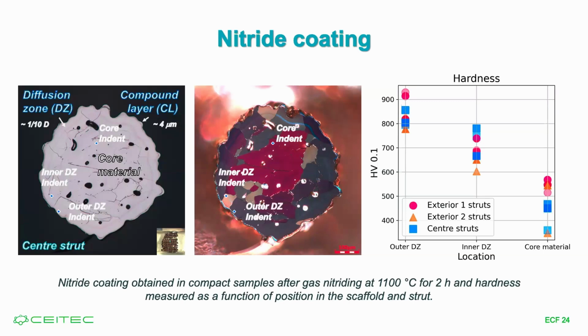And we try to measure hardness of these coatings at the surface, at the diffusion layer, and then in the core material, and we measured it also in different positions in these scaffolds. And these results here show that we are able to achieve homogeneous nitridation within this scaffold.